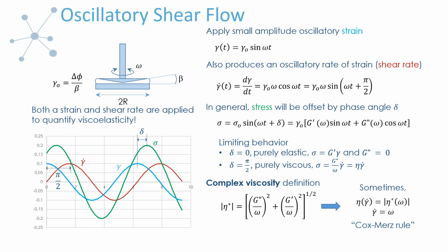The thing that's a little different is that because we're doing a low amplitude strain, the nature of the microstructure for the steady shear experiment as you go to higher and higher rates is much more further perturbed from equilibrium than it is at the higher frequencies, because what matters so much with the oscillatory is the strain magnitude.